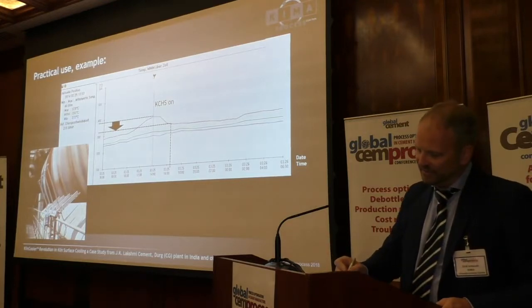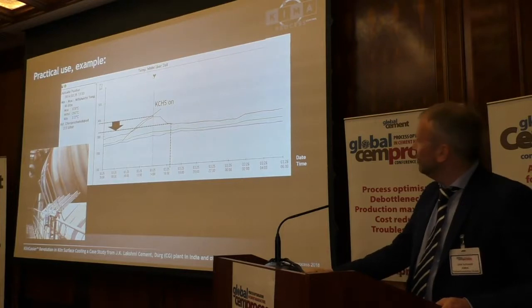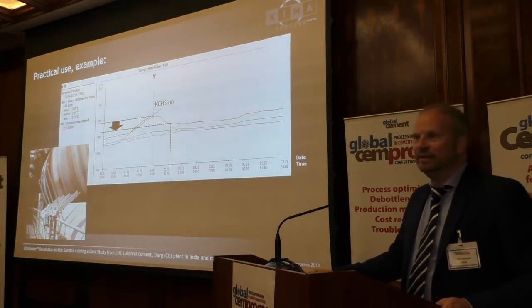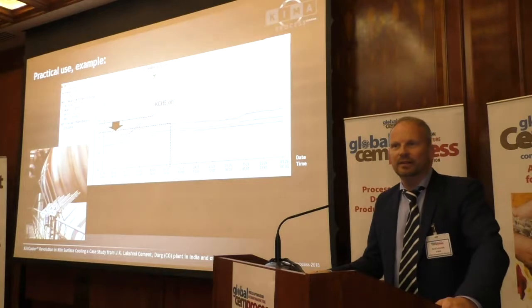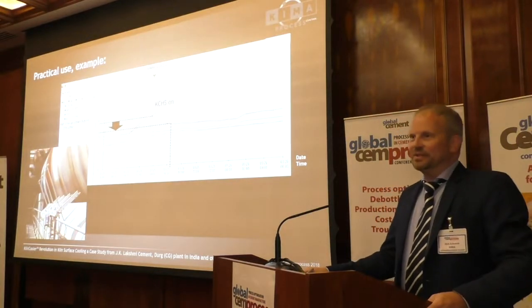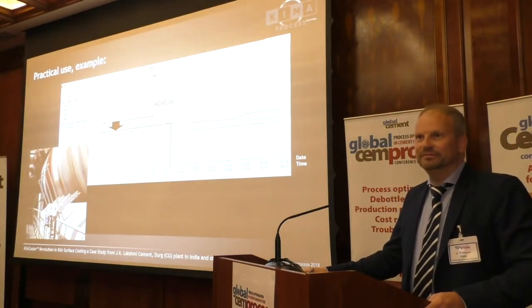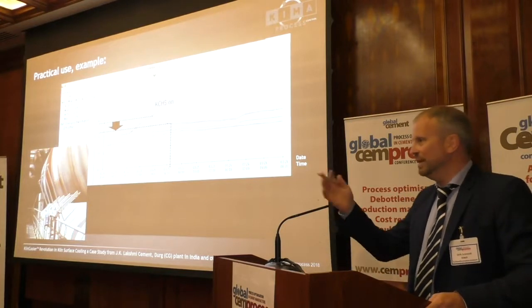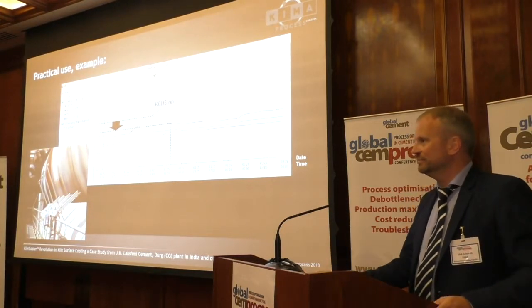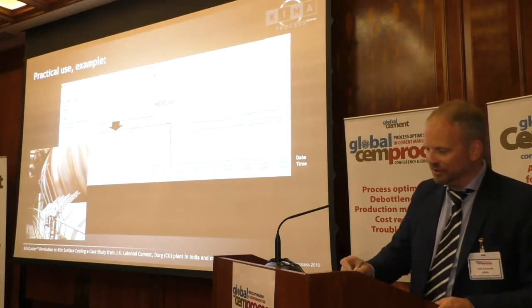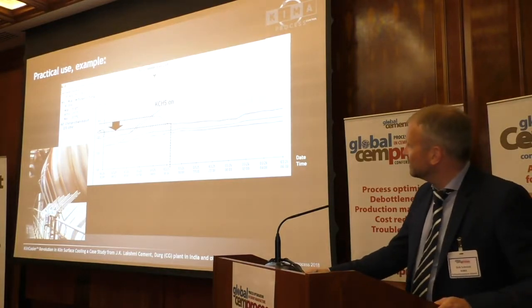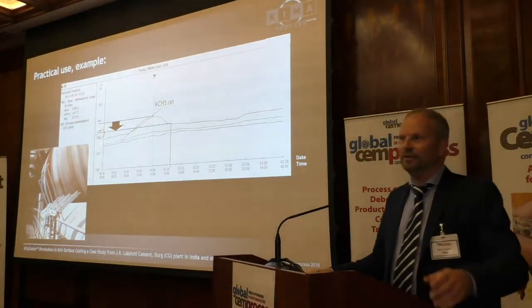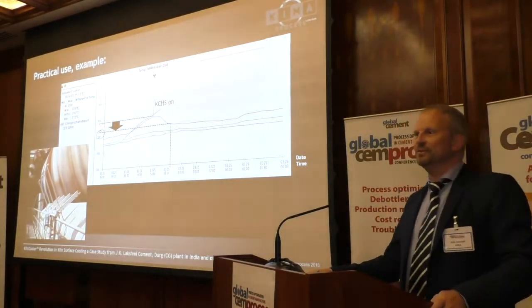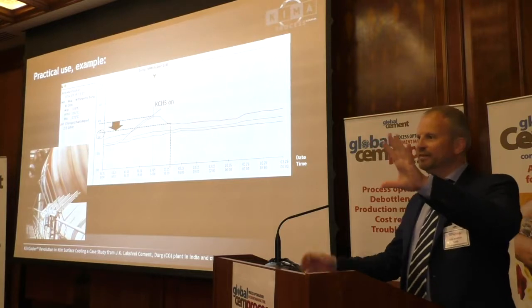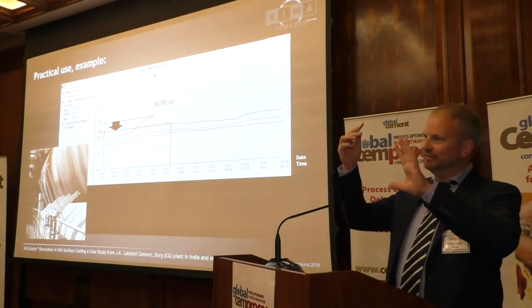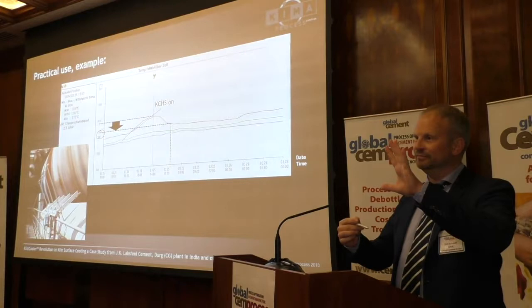Over a couple of times, the temperature in this region was increasing and increasing and increasing. So the operator said to his maintenance team, please move the kiln shell cooler to, let me say, 13 meters, and adjust the target temperature here to approximately 330, 340 degrees. The system is now spraying whenever this temperature is reached and above, not below.